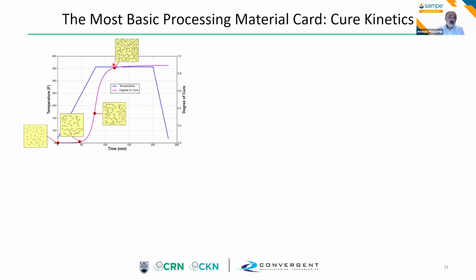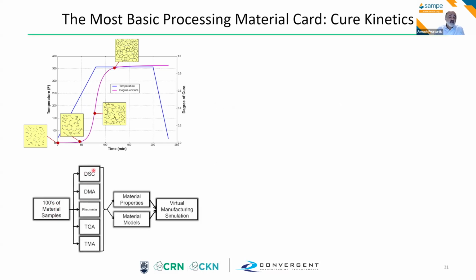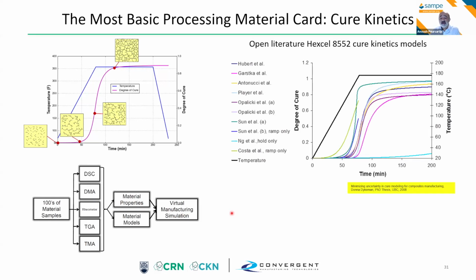So the way we create these material cards is we do lots of tests using a wide range of analytical equipment. And right now, of course, we're focusing on differential scanning calorimetry, say, where we're using heat flow to quantify degree of cure. And you choose your favorite material model equation, and you fit the data to it. So that gives you the material card for that material, and off you go to the races to do the simulation.